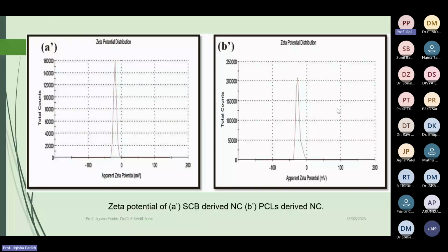Similarly, we have also performed the zeta potential for both the components. If you see this figure, the zeta potential of the nanocellulose derived from both components is coming to minus 25 and minus 19 millivolt. And this is important because it signifies the occurrence of negatively charged functional groups on the surface of nanocellulose.